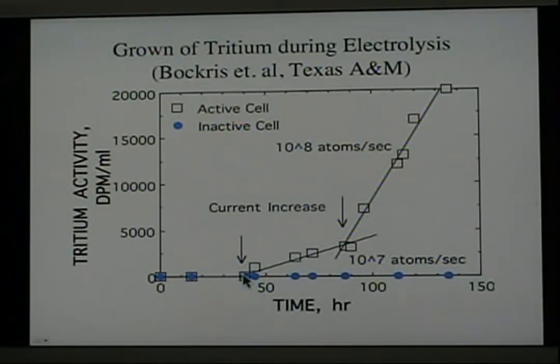First of all, notice that no tritium was produced initially until the current was increased, and then tritium production started. When the current was increased again, the tritium production rate increased. It was very interesting. This was a rather unique experiment because finely divided dendrites were found on the cathode surface. And when this cell was shaken, tritium production stopped, and it did not resume until these dendrites had reformed. Notice also a cell run at the same time that was not active but was subjected to the same conditions showed no increase in tritium.